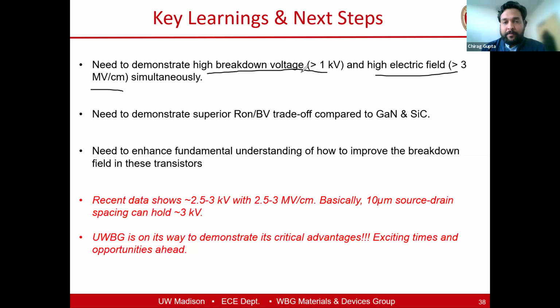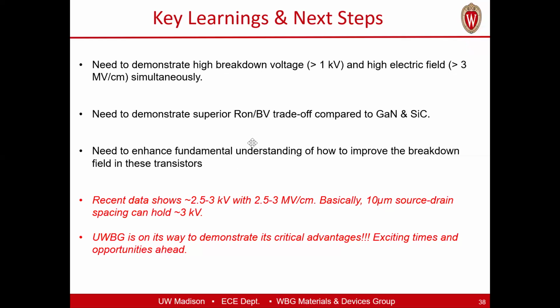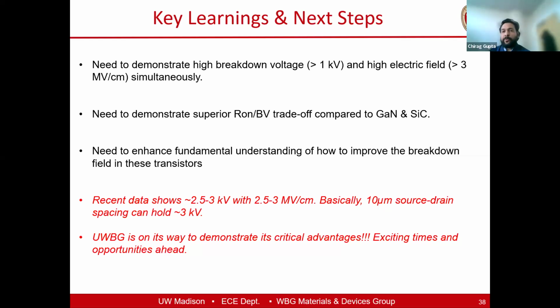The first question is: in unidirectional GaN high electron mobility transistors, substrates are typically tied to the source. How do you handle the substrate in the bidirectional GaN high electron mobility transistor? In our case, when we were dealing with silicon substrate, we kept our substrate floating. And in sapphire, since the substrate is insulating, I believe there was no real need to bias the substrate.